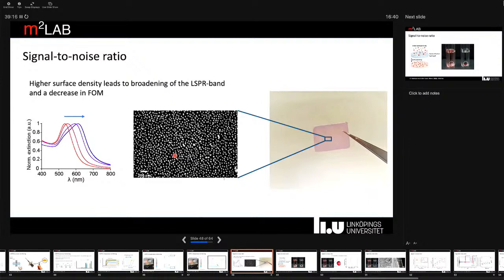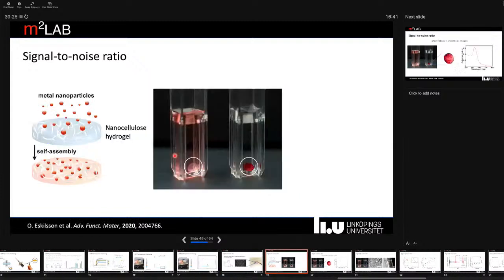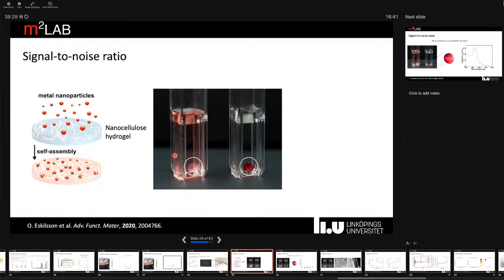So we started to look at possibilities to instead increase the number of particles in the third dimension by using three-dimensional substrates. And one such substrate that caught our attention was nanocellulose hydrogels. These are essentially biopolymeric, water-rich materials, but can be produced with really high quality and reproducibility. And what you see here in the bottom of this cuvette is one of these cellulose membranes. And we wanted to develop an approach where we use self-assembly of particles in here, so we can start with well-defined particles. There have been a number of papers published on attempts to synthesize particles in nanocellulose, but then you don't have the same control over particle size and composition and shape as you can if you prepare particles separately and then adsorb them in the cellulose.